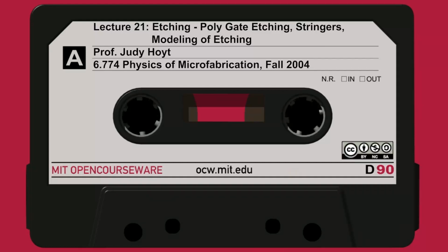Sometimes, by the way, here on slide 19, I've been calling these things stringers. Stringer is the derogatory term. Stringer usually means something that was left behind that you didn't want there. Sometimes a stringer is something we want. In fact, when we want it, we give it a positive name. We call it a sidewall spacer. So we often use anisotropic etches without an over etch to get a sidewall spacer intentionally.